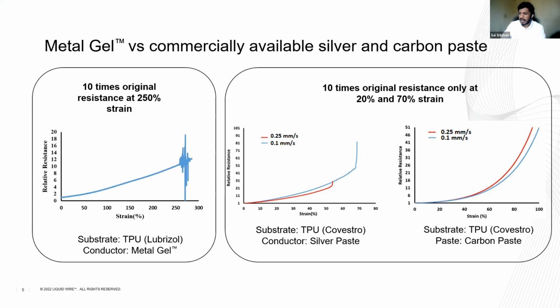In other words, the metal gel performance is completely dependent upon the substrate that we use to laminate the metal gel. The TPU that we constantly use gives virtually hysteresis-free stretch conditions for 100%, and we can stretch it over 1 million cycles. So depending upon that substrate, we can define the performance of the metal gel.